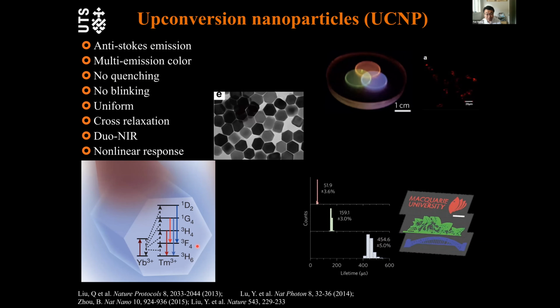Based on those properties, these nanoparticles have really strong anti-Stokes emission and are multicolor. For example, if you change the dopant concentration, or change the dopant like erbium and thulium, different types of material, you can also select different emission bands. You have multicolor. For example, this one from Xiaogang Liu's group, they can do 3D display with full color. And because it's atomic transition emission, unlike the dye or the quantum dot, it doesn't quench and doesn't blink. So it's really stable.